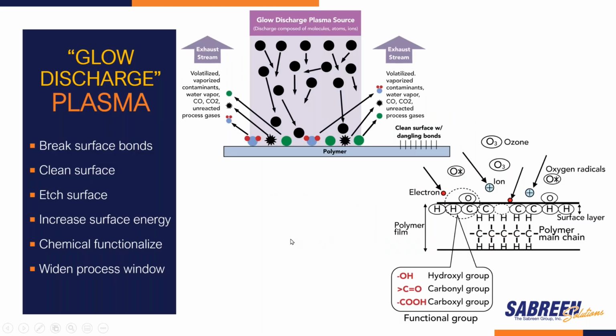Let's now look at what happens during a plasma. When we talk about plasmas for surface pretreatments, I'm actually going to be using a more accurate term, glow discharge plasma. So how do these plasmas actually work? The basic chemical and physical reaction that occurs in the plasma source of the pretreatment is free electrons, ions, metastables, radicals, and UV generated in the plasma impact the surface with energy sufficient to break the molecular bonds on the surface. This creates very reactive free radicals on the polymer surface that, in turn, can form cross-links, or in the presence of oxygen, react rapidly to form various chemical functional groups on the surface.